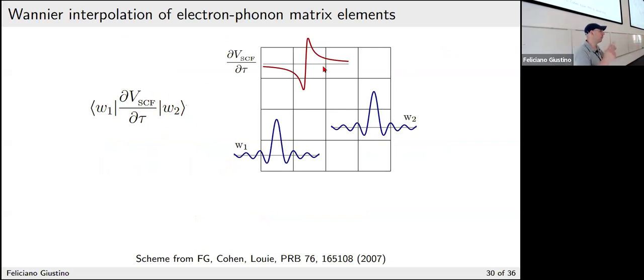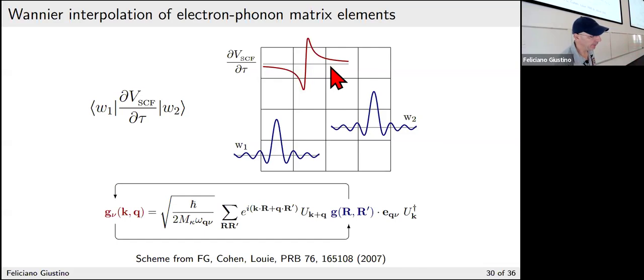If those three things are far away from each other, maybe the matrix element will be 0 because they don't overlap, okay? So what that means is that, in this representation, you only need a few matrix elements, where these things are close to each other, that need to be maintained and calculated in order to proceed with your calculation. So there is a significant saving coming from the use of Wannier functions because it takes into account the physics of the localization of this problem. So practically, this leads to an interpolation formula, which is going to be used in EPW in order to generate many matrix elements starting from just a few matrix elements. That's what we're going to learn throughout some of the tutorials tomorrow and Wednesday.